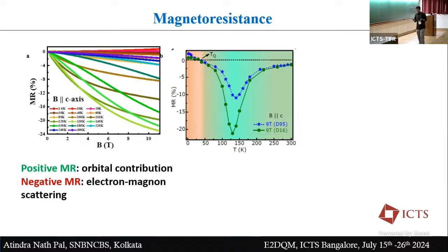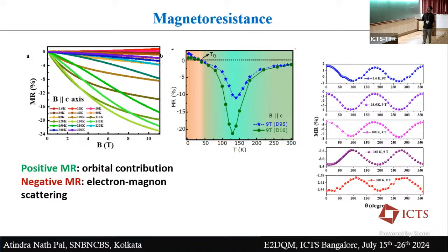So negative magnetoresistance is very common to this kind of ferromagnetic system, because if you apply a magnetic field, you suppress the spin flip scattering and you get a negative magnetoresistance. Okay, but this positive magnetoresistance is very uncommon, because you basically get the orbital contribution. In this case, there is almost negligible magnon contribution in this region. Okay, so I'll show you the experimental result first, and then we'll discuss. We also observe, if you measure the anisotropic MR, angle dependent MR, you can see very nicely near the spin reorientation transition, this phase shift, you get like a cos-like curve to a sine-like curve, something like that.